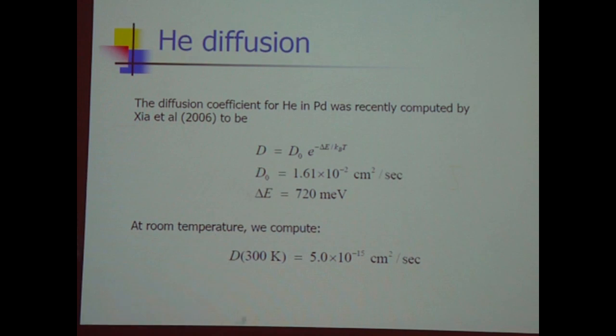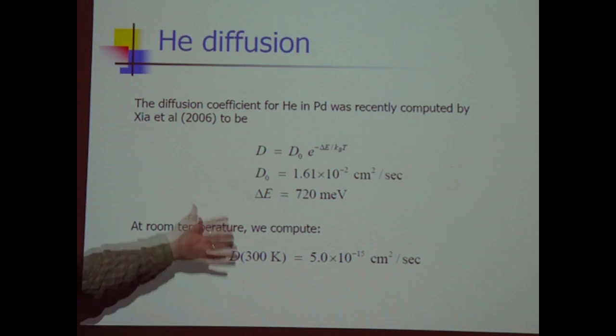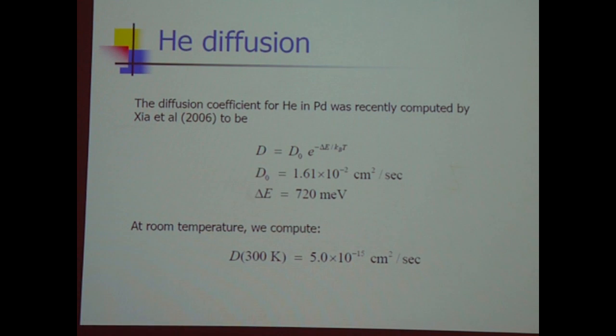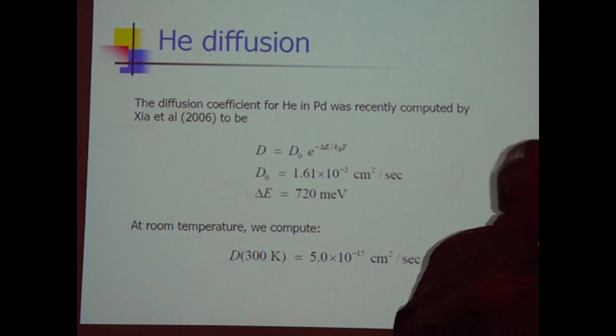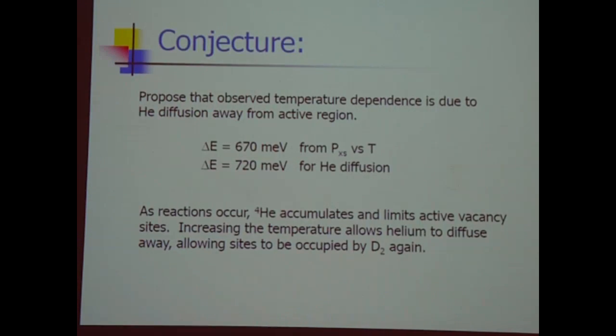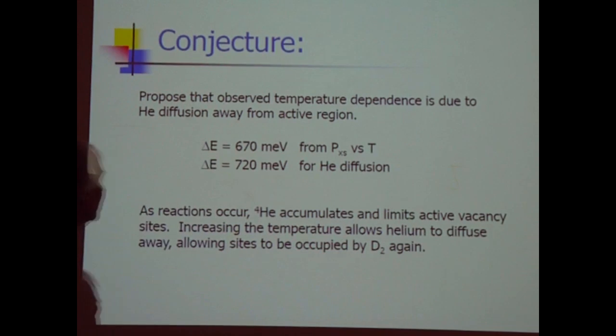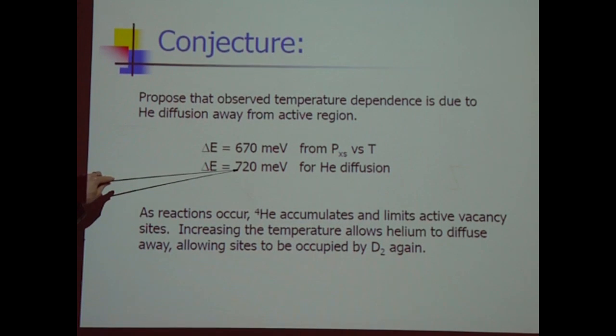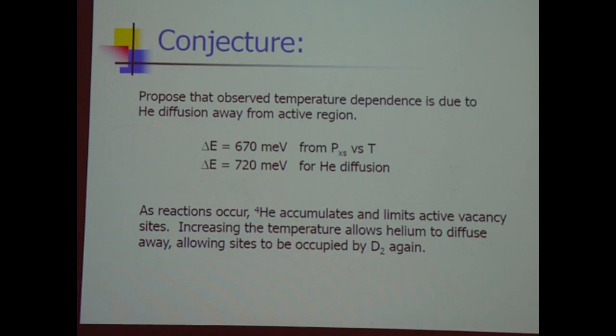So the diffusion of helium-4 through palladium was computed by Xia, and basically the barrier number calculated was 720 milli-electron-volts, which basically is the same number as Mitchell got, and essentially the same number as Storms gets. And you can calculate the diffusion coefficient as being this. This is not the world's largest number. It's actually hard to get helium to move through the lattice. So, for example, here's Storms' number, here's Xia's number for helium, and I'm looking at that, and they look sort of close to me.